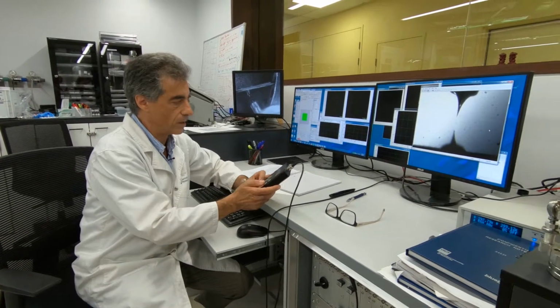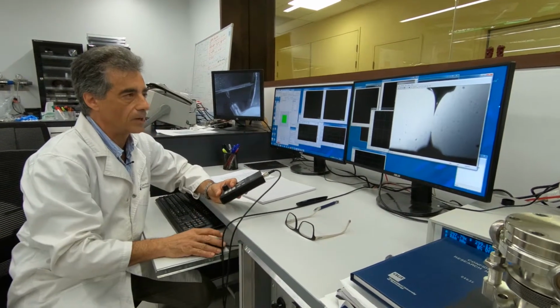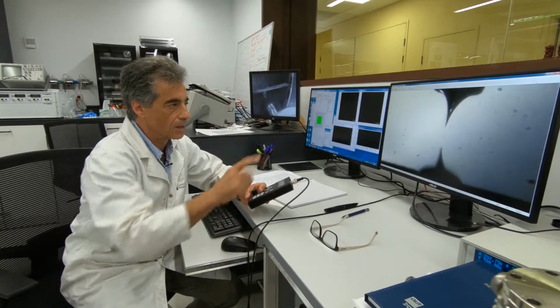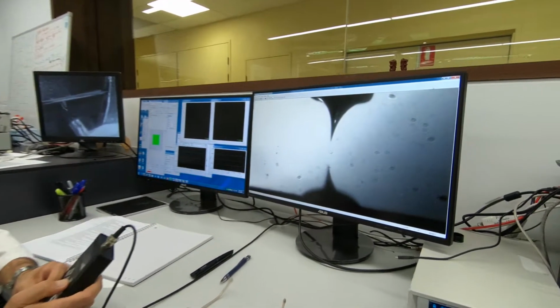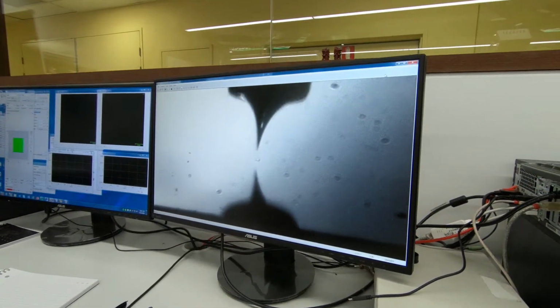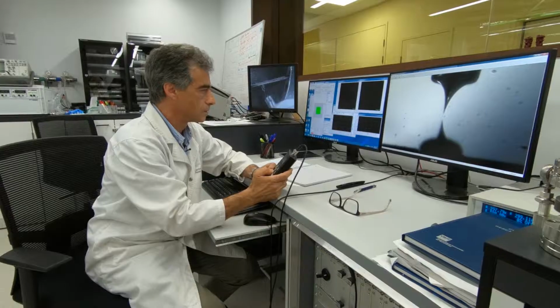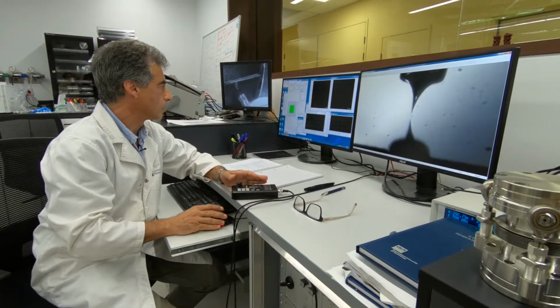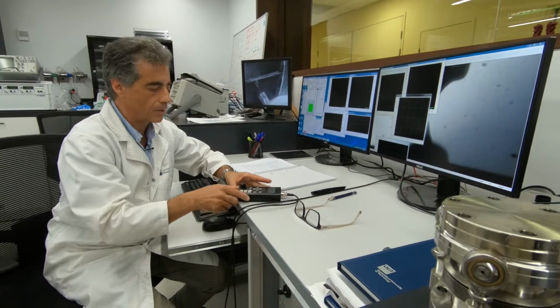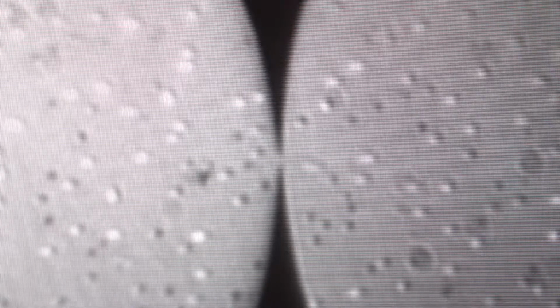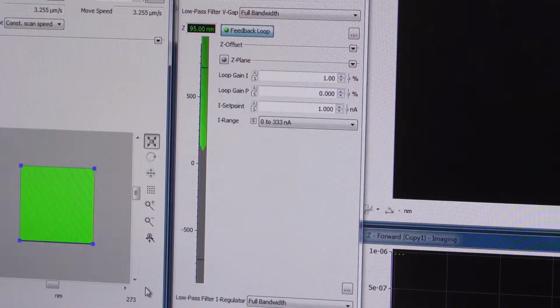Okay, when the tip is close enough, we can have a look at the high magnification microscope window that is here, and we can start approaching slowly. You can see that this moves very easily if you touch the system. And now we are going to set up the automatic approach. The program will find the optimum distance to obtain the required tunneling current. By controlling the current flow, we can control the distance between tip and sample to the atomic level. Here we are. Tunneling current detected.